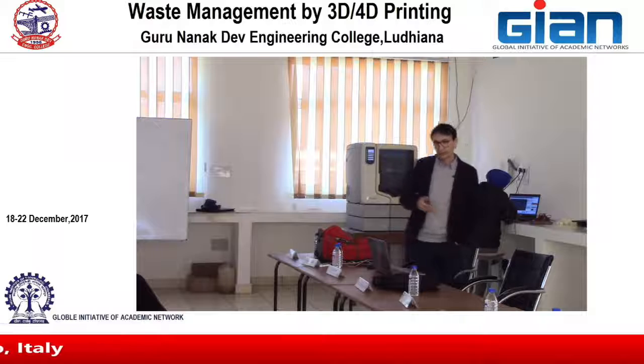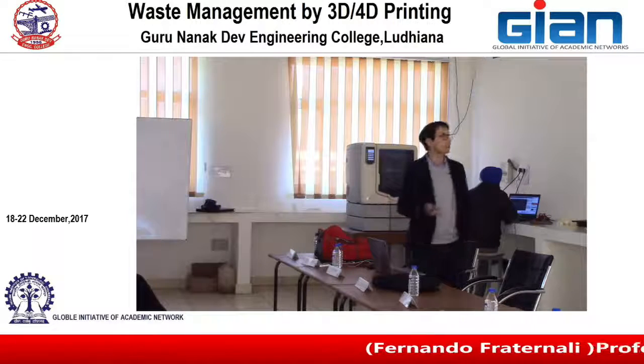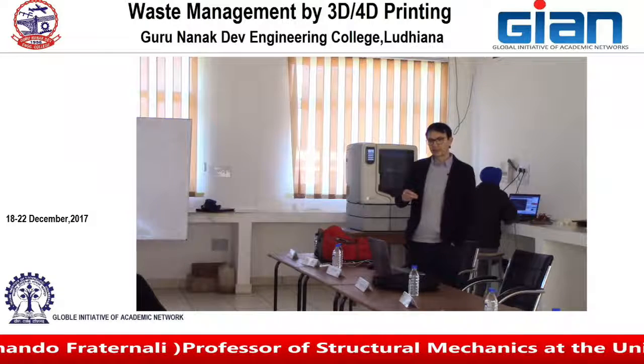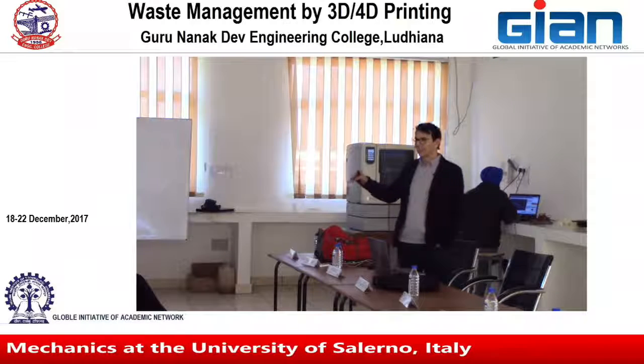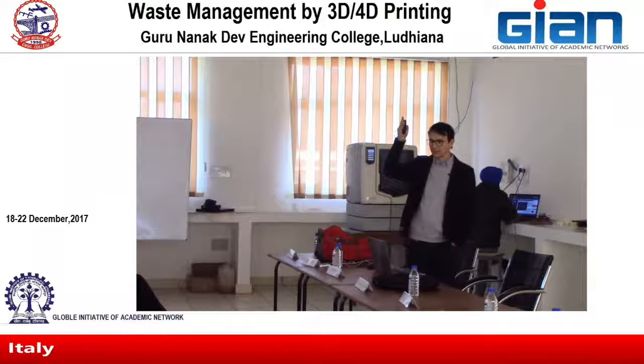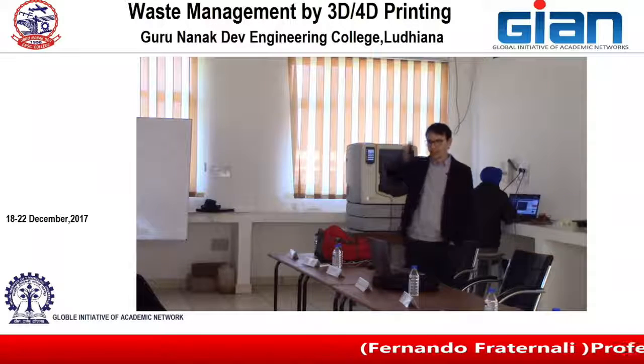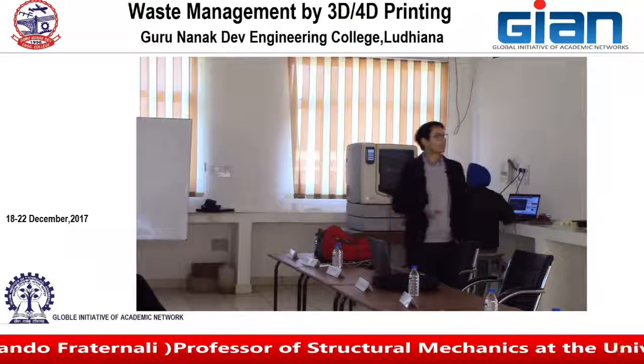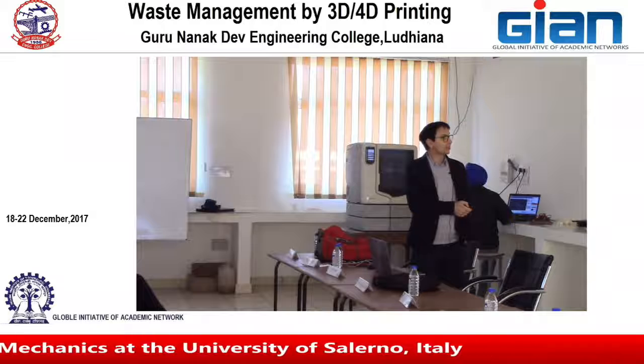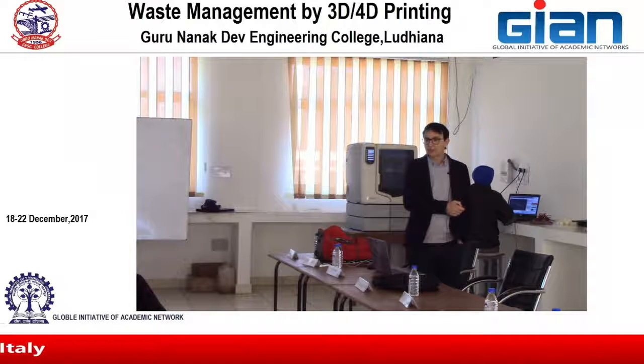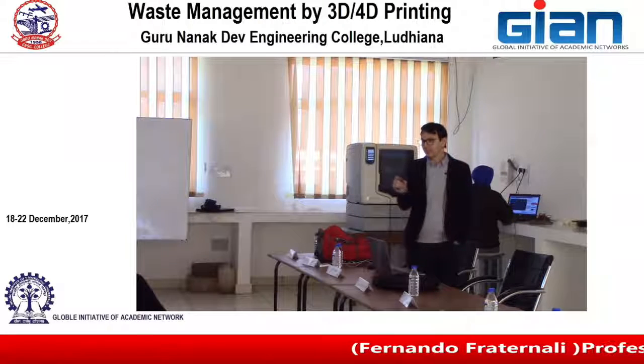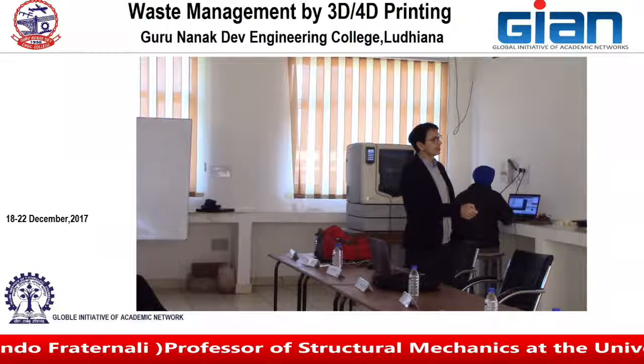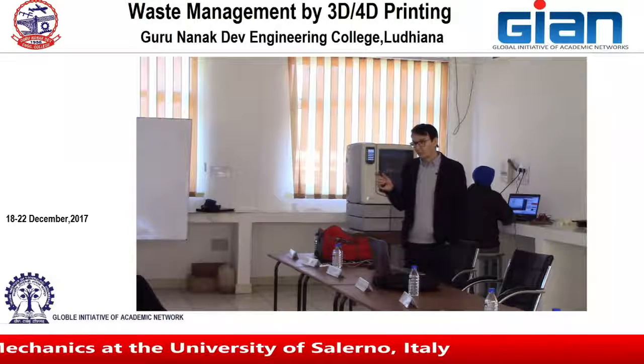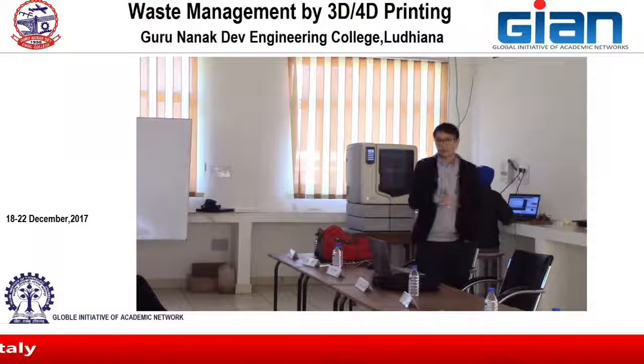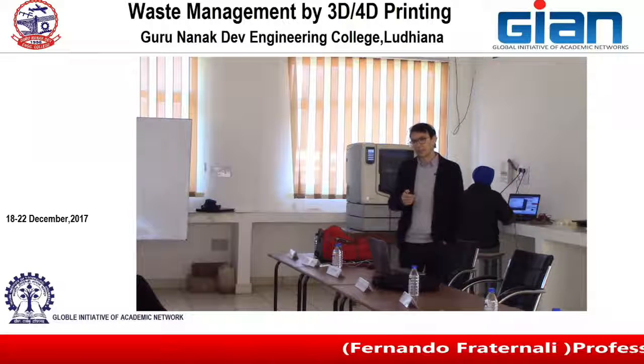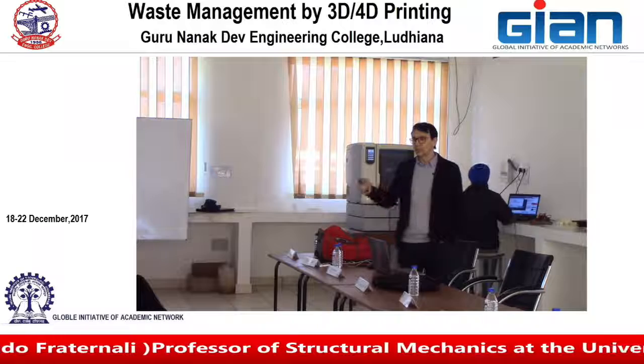And then we defined the ductility indices. Ductility indices are basically the ratio between the equivalent post-failure strength, so the residual strength, and the first crack strength. The first crack strength is in correspondence to the peak load, while those other quantities, F equivalent 0.6, is the residual strength in the 0.6 millimeters crack opening displacement regime, and this other one is the 3 millimeter crack opening displacement regime. Those are the residual strengths, and if you divide the residual strength by the first crack strength, you obtain what is called the ductility index.